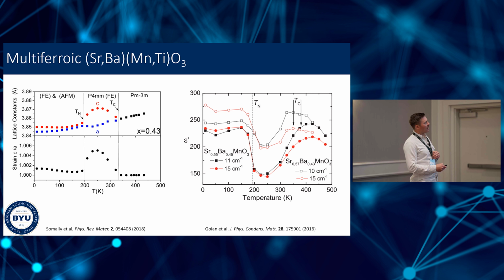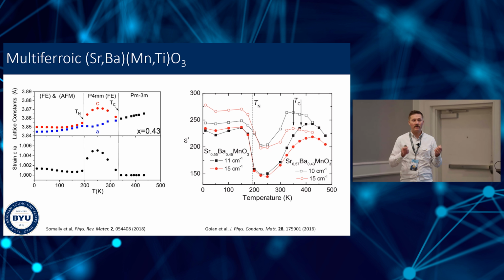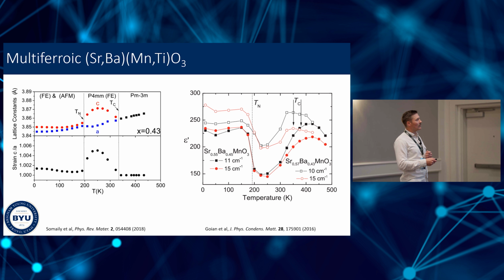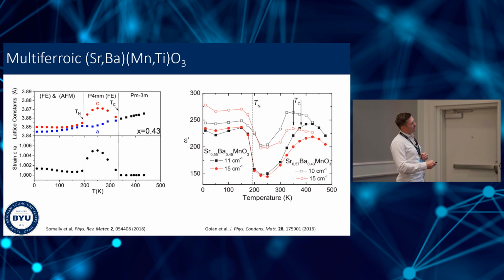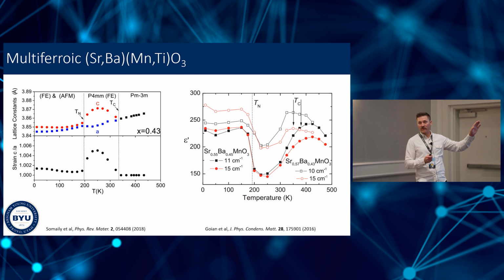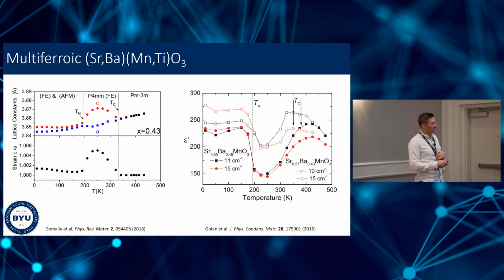And we see that there's a strong response in C over A to the development of the magnetic order, all right? So C over A, that ratio is proportional to the ferroelectric moment, the net electric dipole moment, I should say. And so C over A decreasing in response to the development of magnetic order, that is evidence of this magnetoelectric coupling, so the interaction between the ferroelectric behavior and the antiferromagnetic behavior. So this is the multiferroic nature of strontium barium manganese oxide.